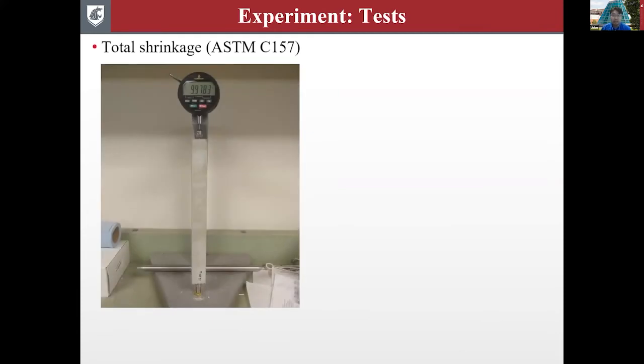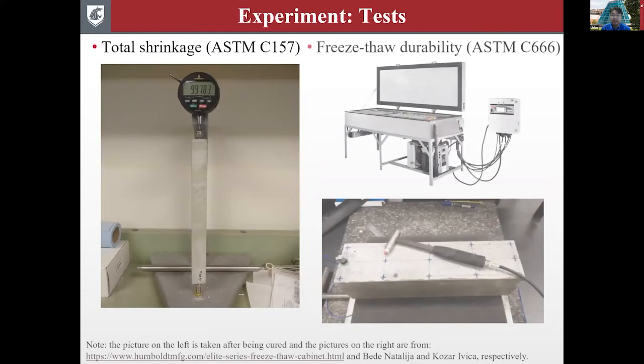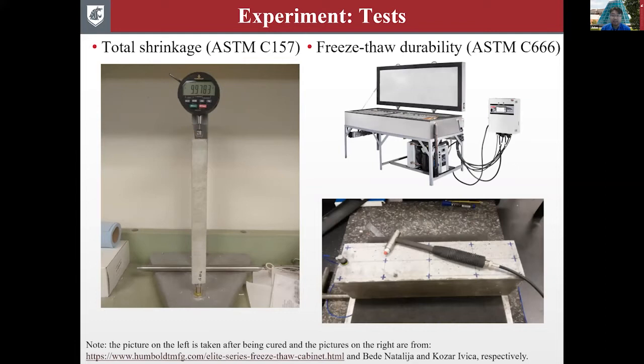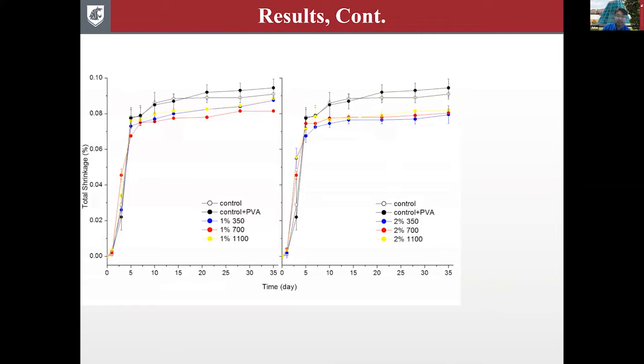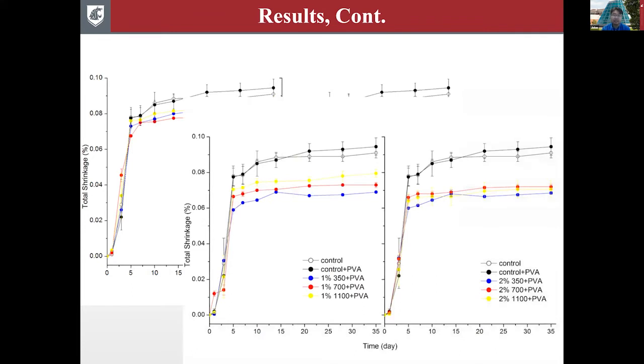And we conducted the shrinkage tests based on ASTM C157 during the 35-day curing period. And we conducted the freeze-thaw durability tests based on ASTM C666 by obtaining the relative dynamic modulus of concrete specimens over freeze-thaw cycles. So here's the result of shrinkage. As we can see here, with the addition of urea-formaldehyde microcapsules alone, the total shrinkage is reduced by 10% by the end of the 35-day curing period. And with the addition of microcapsules and PVA microfibers, the reduction of total shrinkage by the end of the 35-day curing period can be as large as 25%.